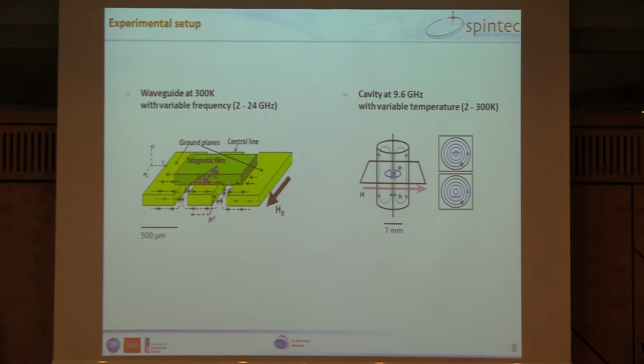So we've used 2 different techniques. These techniques were also introduced earlier this week. So we've used a waveguide at room temperature, but the advantage of this waveguide is that it's a broadband coplanar waveguide, and we can work with variable frequencies. And this way we can work out the inhomogeneous broadening of our system. So this is a technical parameter. I'm not going to enter more into these details. We use also a cavity at a fixed frequency, but this time we can vary the temperature, and we will see in the talk that there is some interest in varying the temperature.